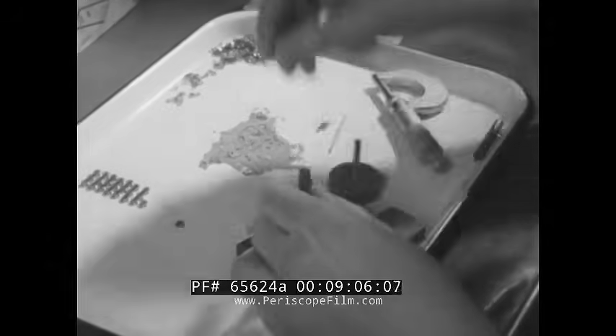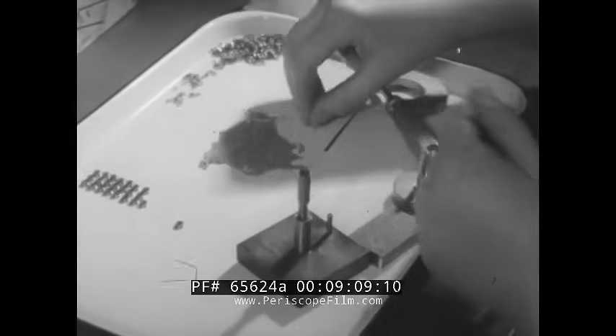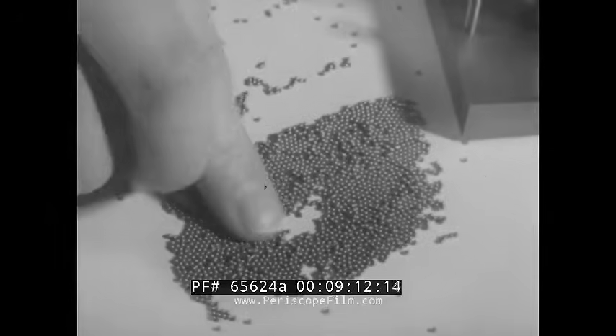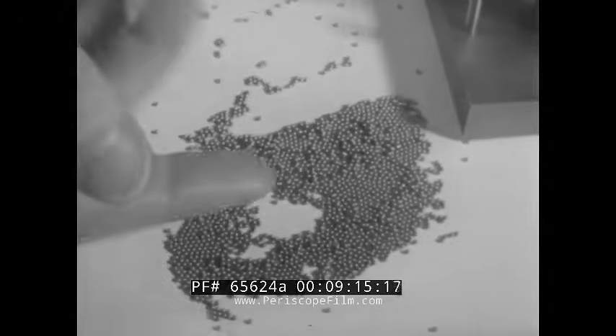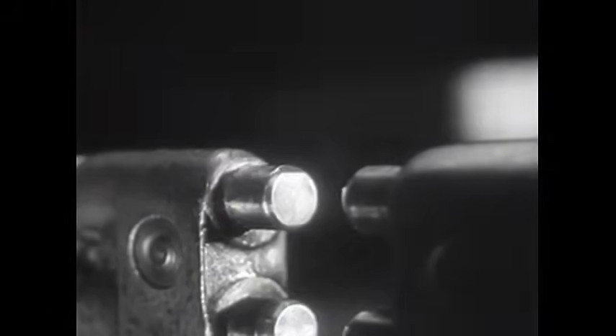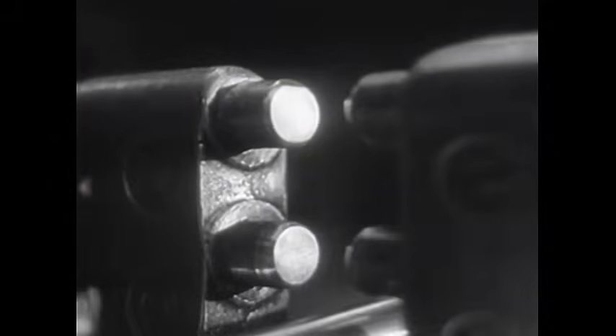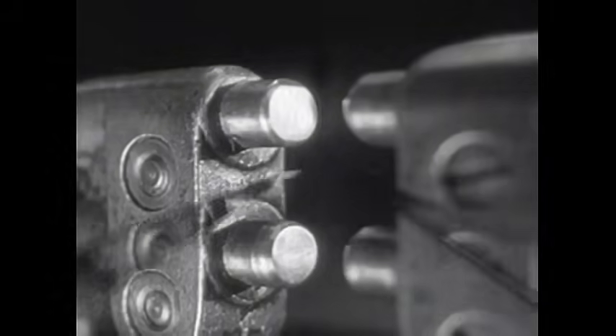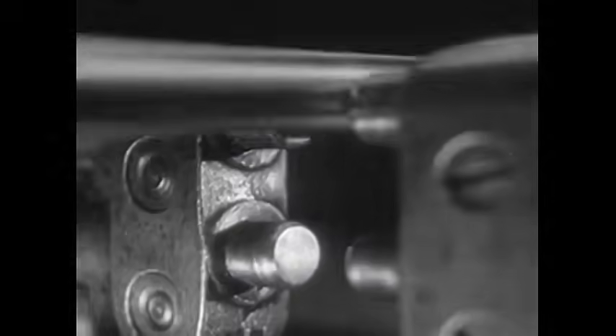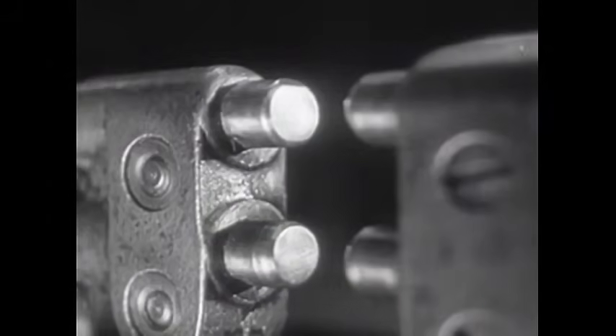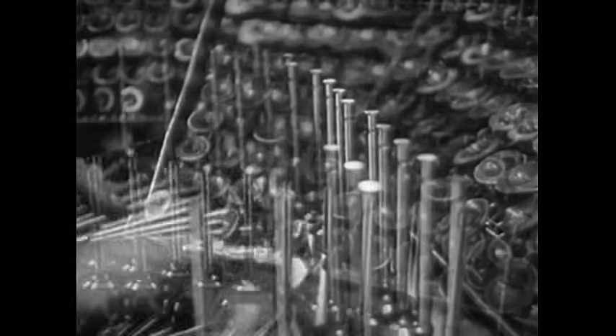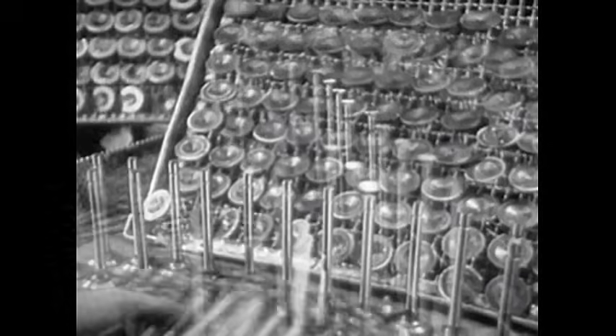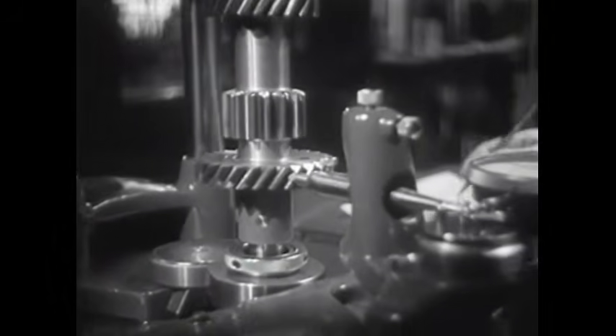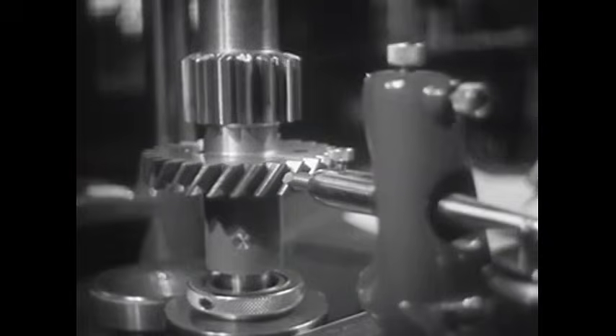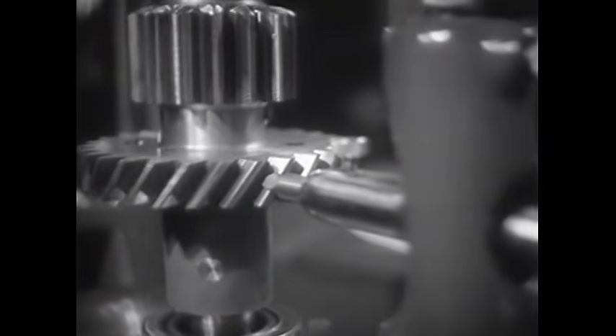The sequence is deliberate. Rough the balls while the steel is soft and easy to cut, because removing large amounts of material from hardened steel is slow and expensive. Then harden. Then grind again, now on hardened steel, to restore and improve the geometry that hardening disturbed. Grinding after heat treatment uses the same principle as before, the balls rolling in grooves between a plate and an abrasive wheel, circulating repeatedly, the same orientation blind convergence, but now working on steel hard enough to hold the shape it is given. Do it in the wrong order, and you either wear out your tooling on hardened steel or you deliver perfectly round balls that warp in the furnace.